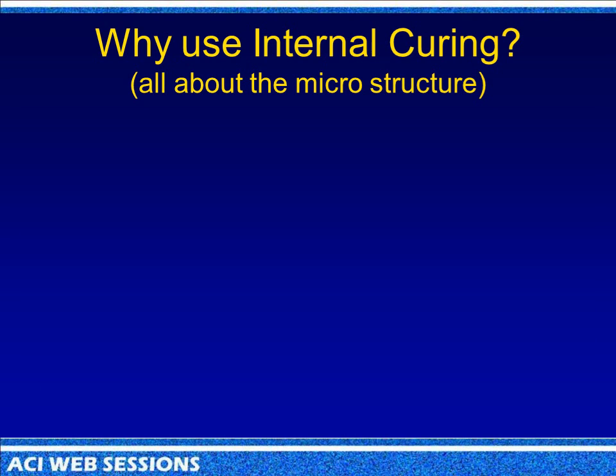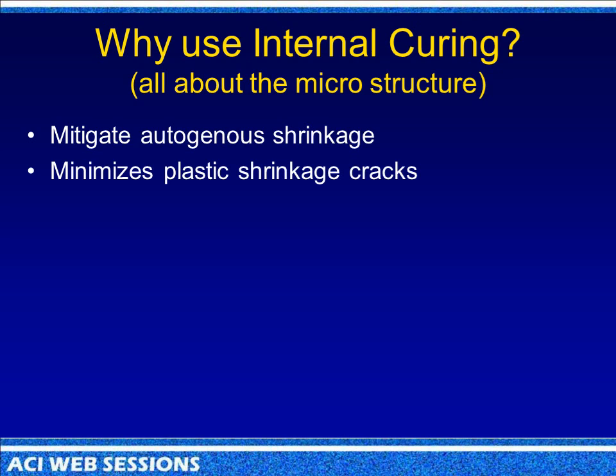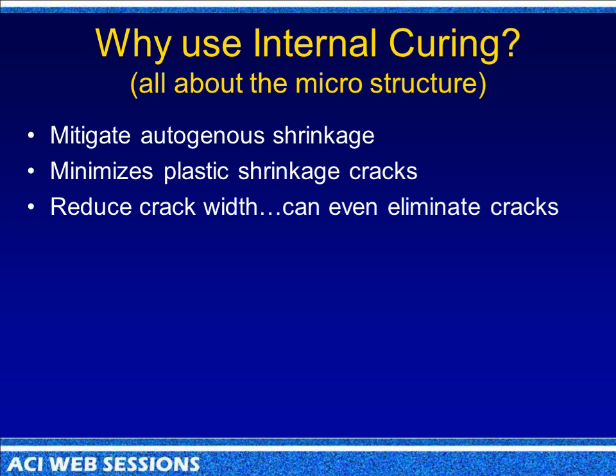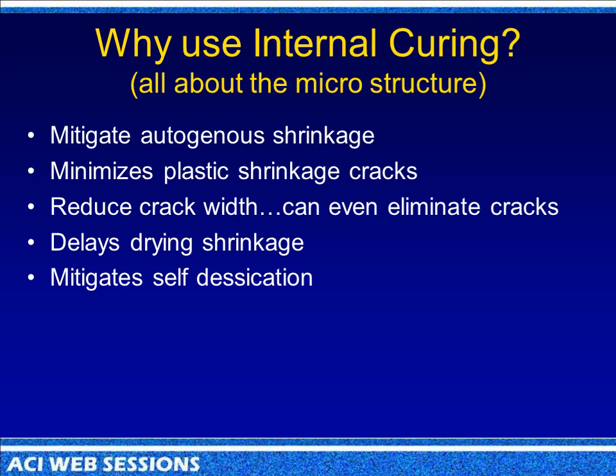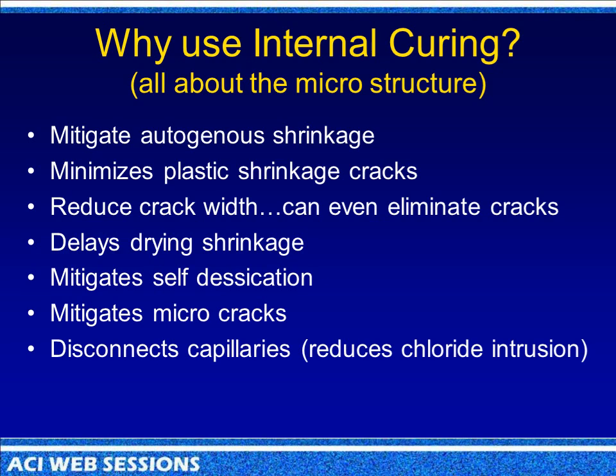So why use internal curing? Well, it mitigates autogenous shrinkage. It minimizes plastic shrinkage cracking. It reduces crack width and can even eliminate cracks. It delays drying shrinkage. It mitigates self-desiccation. It mitigates micro cracks. And it disconnects the capillaries, and it reduces the chloride intrusion, and it gains strength. Now, all I can say is, wow.